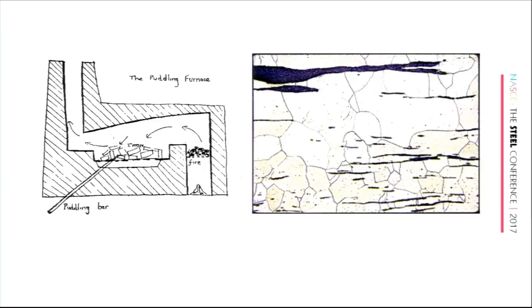So when you go look at an old anchor and it looks like a piece of wood for the shaft, but it's rusted, that's because it's wrought iron, and it only rusts until it hits one of these glass layers and stops. And since they forge it and fold it, forge it and fold it, these are long stringers of silica, and so it looks fibrous. And so people used to think if you wanted ductility, you wanted a fibrous fracture instead of a brittle appearing fracture, and part of that came from this wrought iron.